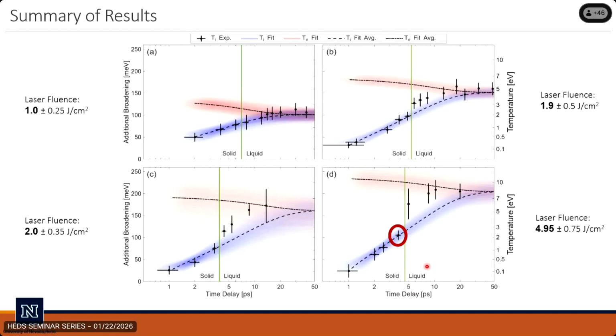But the first thing we wanted to do was write a paper that said we can measure temperature in HED systems. That was what we wanted to write because it's never been done before. And we essentially put all our eggs in the one basket of this one point right here. If you look at this point, this is a measurement of the ion temperature. And if you go across, you'll see it's about 20,000 Kelvin. So it's 2 eV, 20,000 Kelvin.